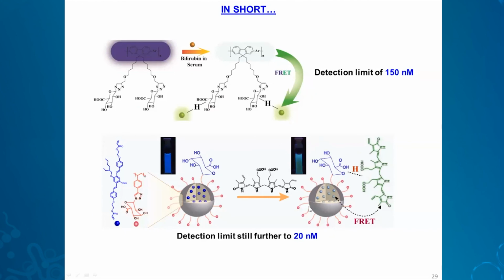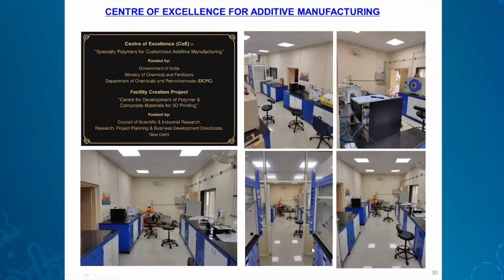So in short, what we have done here is that for the bilirubin detection, we have done two systems, one with the polyfluorene and another with the polystyrene. With the polyfluorene, we could go up to a detection limit of 150 nanomolar, and with the polystyrene system, we could go even down to 20 nanomolar.